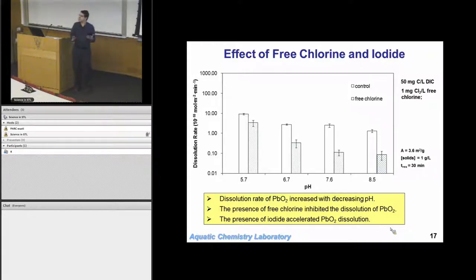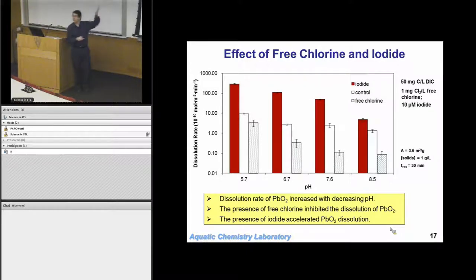If we add free chlorine, as we would expect, it dissolves less quickly. Okay? So we already kind of knew that. Free chlorine could make the lead 4 oxide less soluble, and it also makes it dissolve less quickly. If we have a reductant, which is the opposite of an oxidant, if we have some reductant in the water, it can make it a lot worse. Because this is a logarithmic scale, this would say that it's really made it more than 10 times worse. And so this really exacerbated the problem.